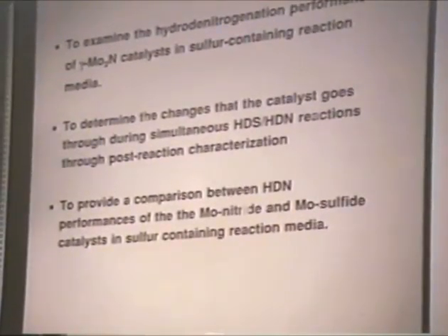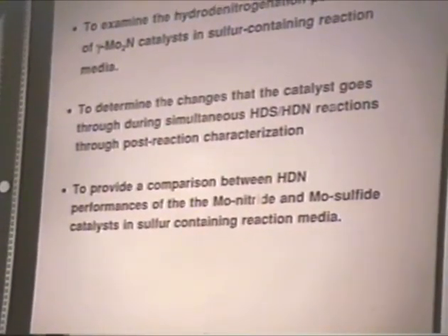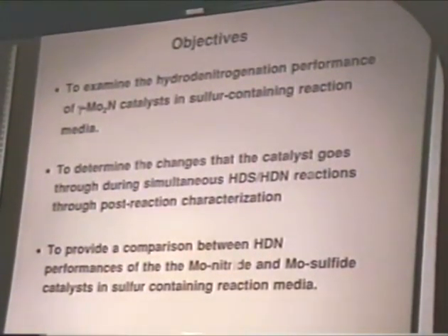The objectives of this work have been to examine the hydrodenitrogenation performance of molybdenum nitride catalysts in a sulfur-containing reaction media. This is really the key, not only looking at the hydrodenitrogenation activity, but looking at it when there are sulfur compounds present in the system. We also want to determine the changes that take place over the catalyst surface during simultaneous HDS-HDN reactions, through post-reaction characterization, and to provide a comparison, using our other phase of the study, between the performance of sulfide and nitride catalysts after they have been used in sulfur-containing reaction media.